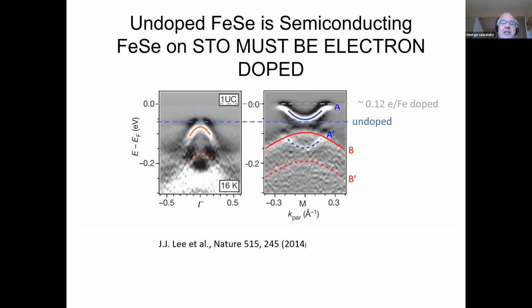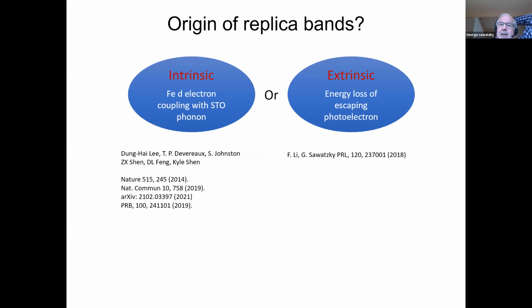It cannot be charge neutral, the whole material. Okay, so if we would take out those electrons, then this material in the rigid band-like sense would be a semiconductor and not a metal in the first place. So this material in the undoped phase, according to this, should be a semiconductor. Now, I just want to talk about these replica bands, but I want to be very short because I want to get to the rest, which is more interesting.